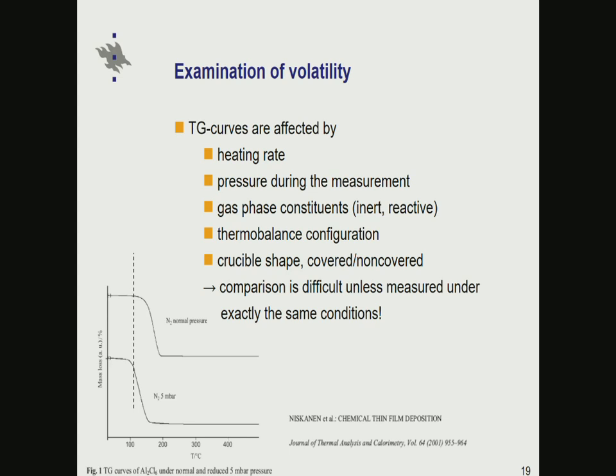In principle, one can do TG measurements with an open crucible. Then what evaporates can easily come off and be swept off from the balance with the gas stream. But sometimes one may also add a cover there. As a result, what evaporates stays in the crucible, and if reaching higher temperatures, it can start decomposing there. And this, of course, affects the outcome quite a lot.